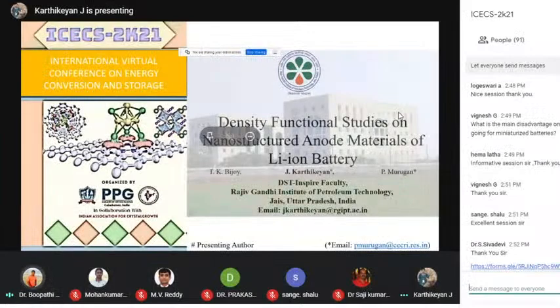And for the first time, he has reported the effect of valence electron concentration on the structural stability and the electronic properties of molybdenum sulfide iodide nanowires. And he has found the best atomistic models of molybdenum sulfide iodide nanowires, in contrast to the models previously reported by many groups. The electronic properties of the atomic models were also corroborated by experimental reports.